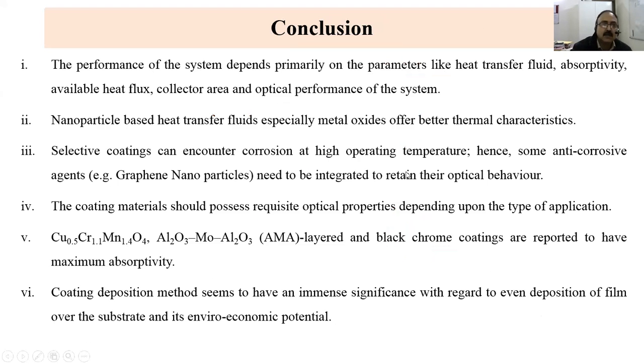Now the conclusions are: the performance of the system depends primarily on parameters like heat transfer fluid, the available heat flux, collector area, and optical performance of the system. Nanoparticle based heat transfer fluids, especially metal oxide, offer better thermal characteristics. Selective coatings can encounter corrosion at high operating temperature, hence some anti-corrosive agent like graphene nanoparticles needs to be integrated to retain their optical behavior.